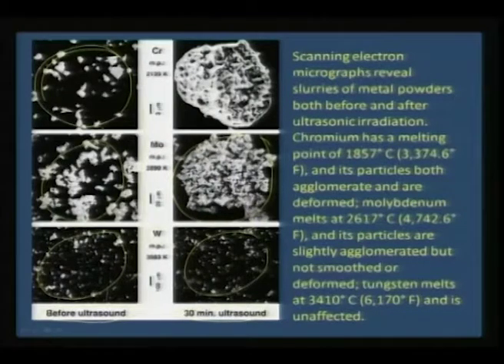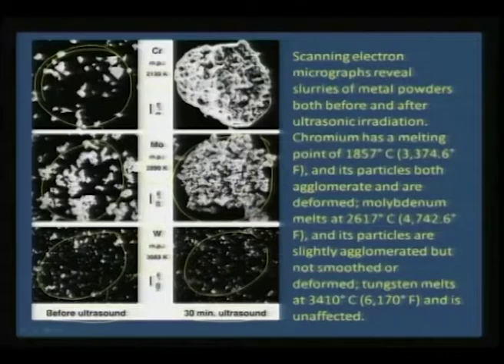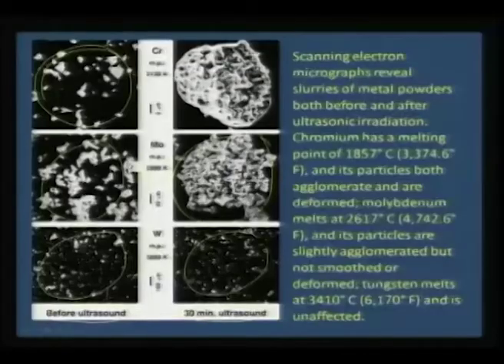What does that mean? If you take chromium, the melting point is around 2130 Kelvin, molybdenum 2890 Kelvin, and tungsten is very high, 3683 Kelvin. So if you try to sonicate these particles, you can clearly see some amount of melting and agglomeration happening in the case of chromium and molybdenum compared to tungsten. So one can say roughly that in this sort of sonication you can realize very high temperatures, to the tune of 3000 Kelvin undoubtedly. Otherwise these particles of chromium and molybdenum will not cluster together. So this agglomeration essentially says not only can we achieve very high pressures, we can also achieve very high temperatures.